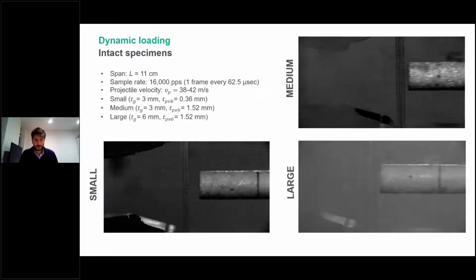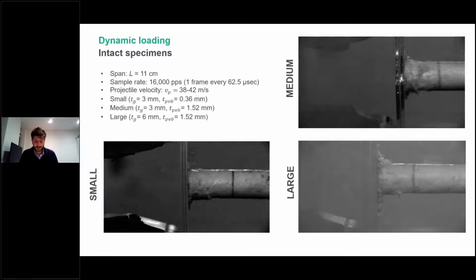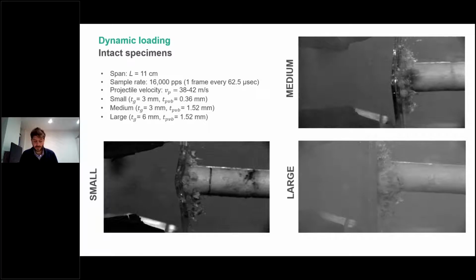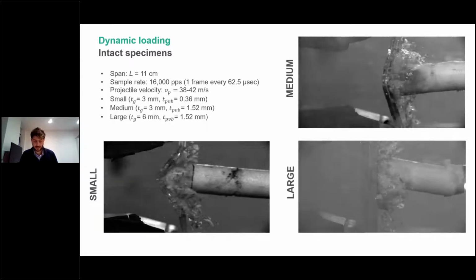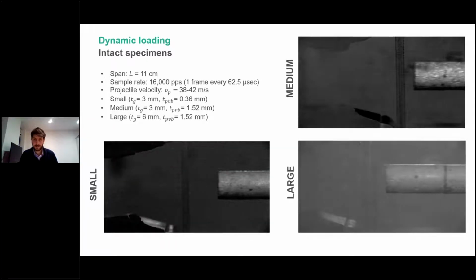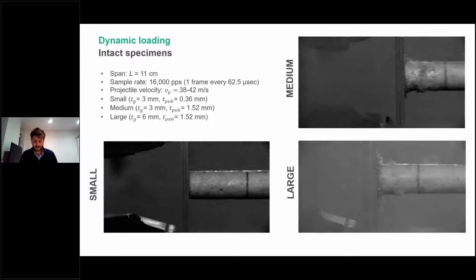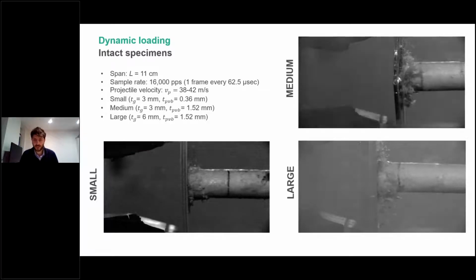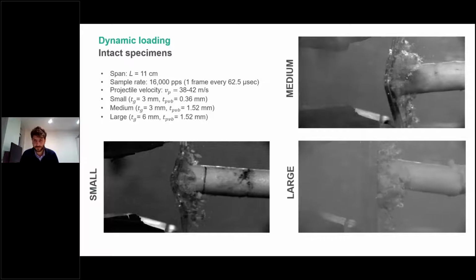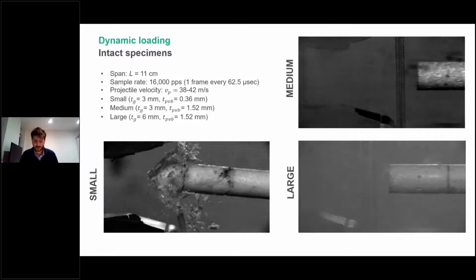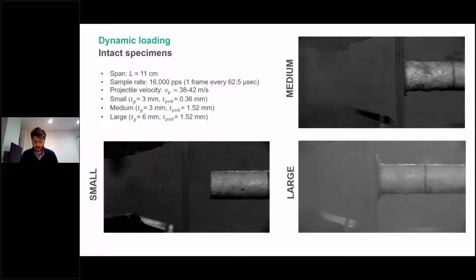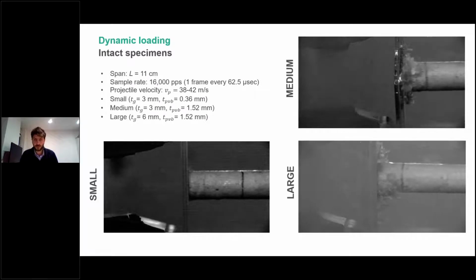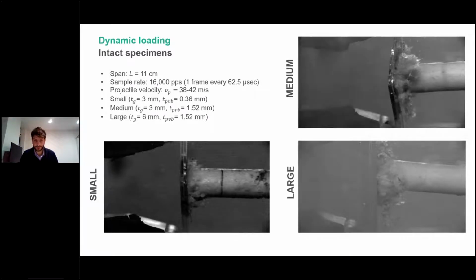The same tests were also repeated on intact specimens to assess the transition from the intact stage to the post-fracture stage. In this case, the loading was not high enough to fracture the larger specimens, as observed in the bottom right-hand video. The response of the smaller and medium cross-section specimens was similar to that observed for the pre-fractured specimens.